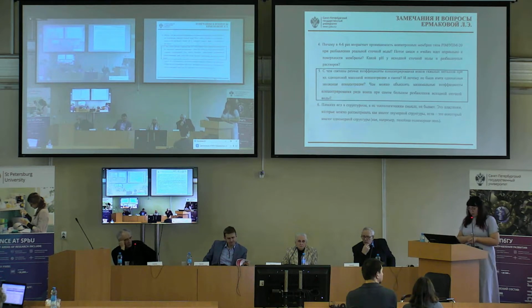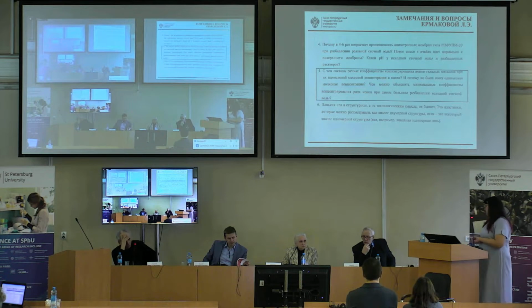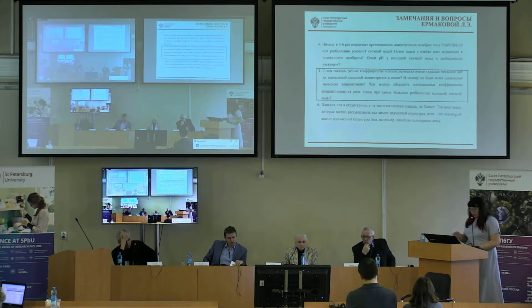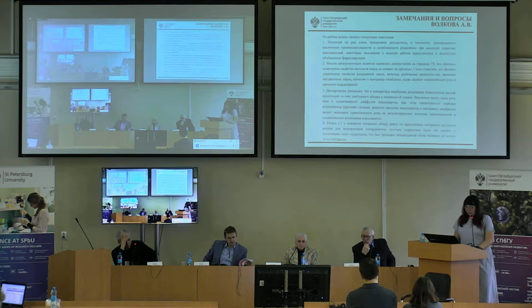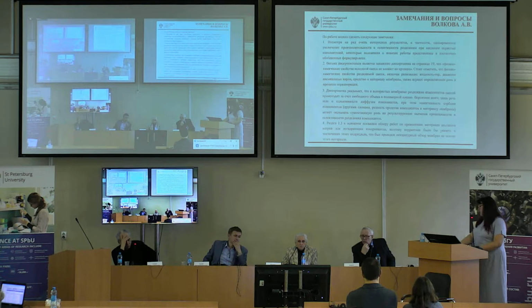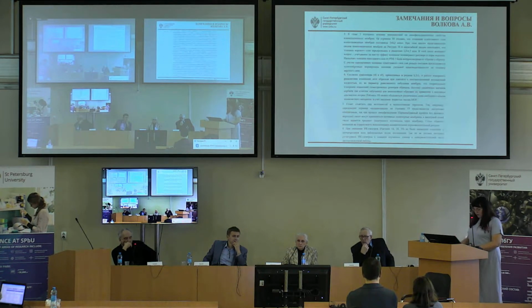The minimum concentration coefficients of a number of ions at the highest dilution of the initial wastewater can be explained by the minimum values of the retention coefficients, since the sorption centers in the membrane in dilute solutions are filled more slowly and a small amount of ions has time to